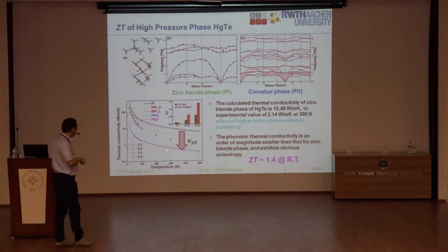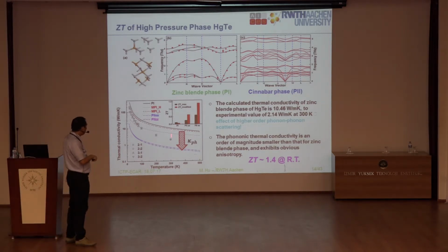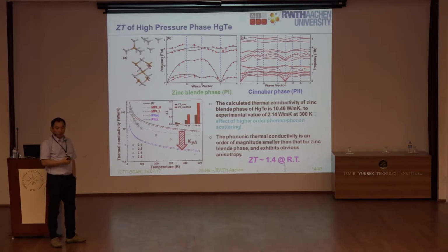So now we are still working on this and trying to compare with experiment. Can you explain what the blue and the pink curves are? This one is for different phases, and the x-axis is a different direction. This one is for the zinc blende phase. And then we have the high concentration and low concentration, and the high concentration gives lower, but it's still a little bit higher than the experiment.